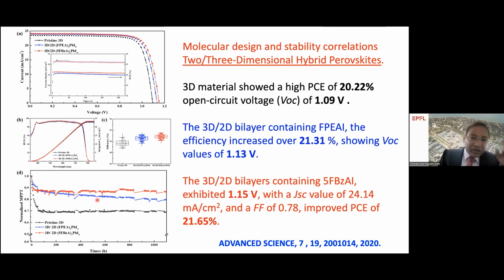However, if you look at the stability data shown on the bottom left side, the reference sample is decreasing the efficiency significantly over 1,000 hours. And the blue curve is the fluorophenylethylamine-containing two-dimensional perovskite, and the pentafluoro-containing one is the red line. So this demonstrates that using this two-dimensional perovskite as an encapsulant layer on top of three-dimensional perovskite increases the efficiency and, at the same time, increases stability significantly.